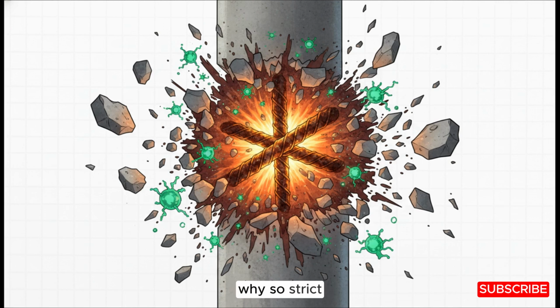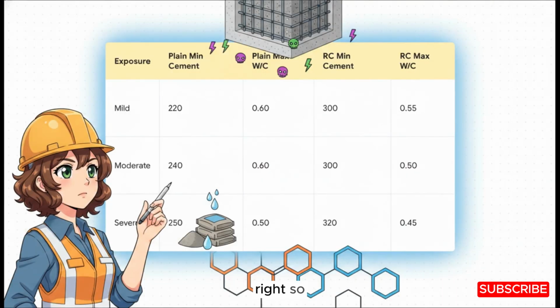Why so strict? Because if you ignore these limits, the chlorides will literally strip away the highly alkaline, protective passivity layer that surrounds your steel reinforcement. Once that's gone, the steel rusts, it expands, and it literally blows the concrete apart from the inside out. To put that into perspective, globally, the corrosion of reinforcement causes a whopping 40% of all structural failures. Crazy, right? So, how do we actually fight this invisible enemy?